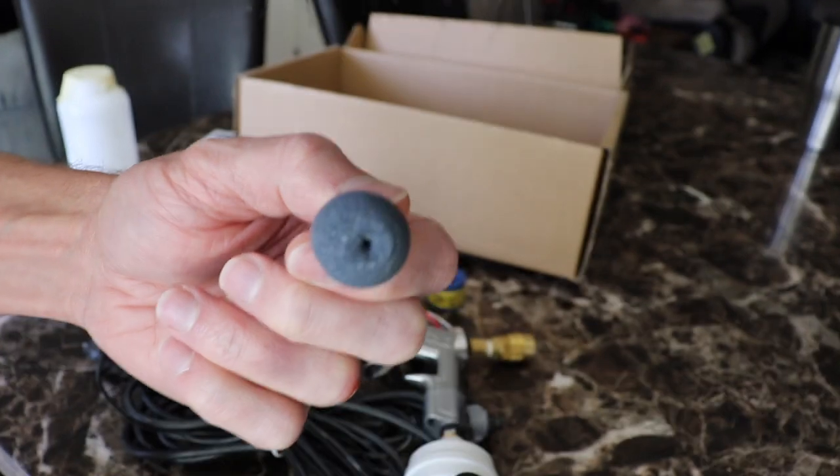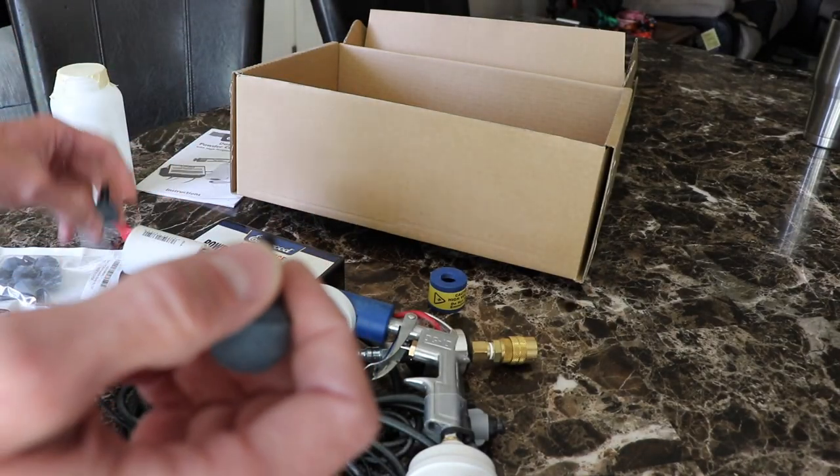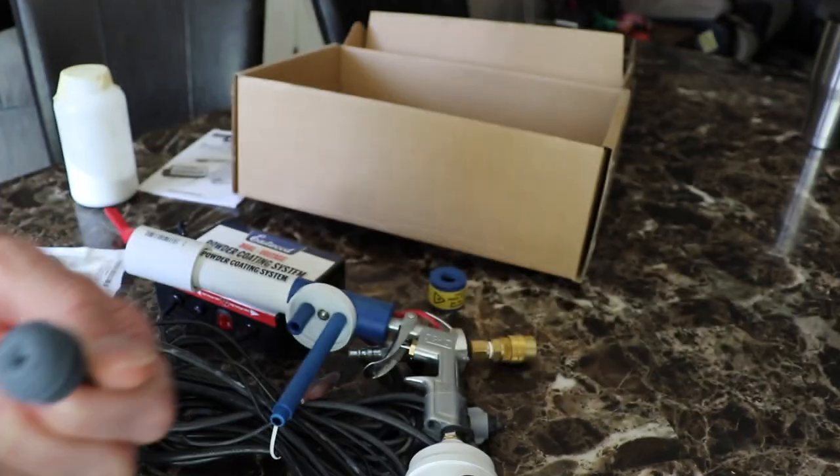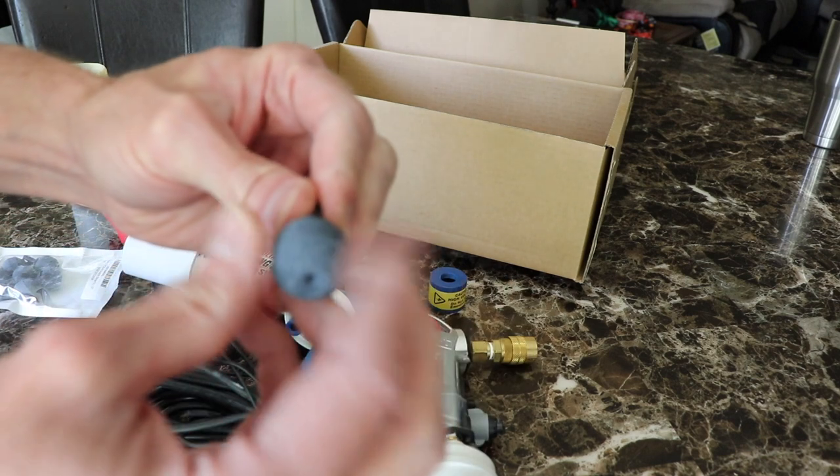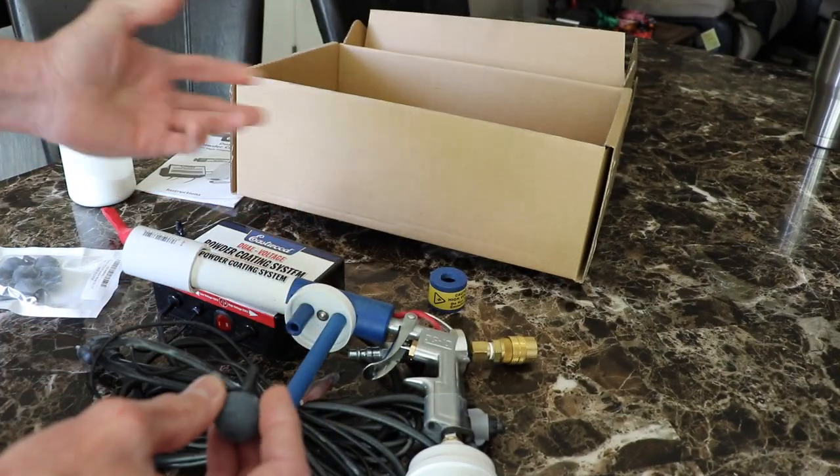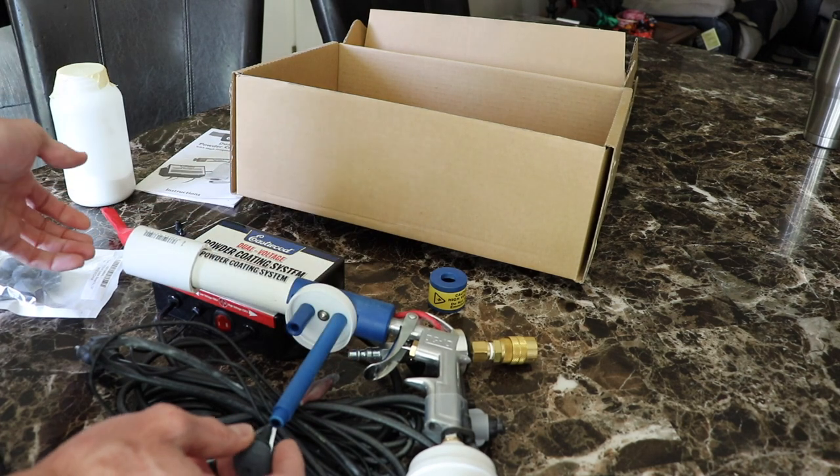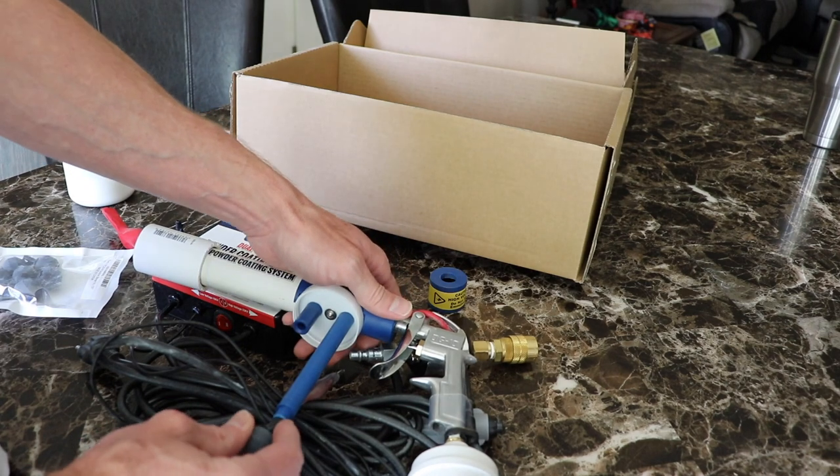But you will have to run a little bit higher pressures putting these air stones on. I usually run about 15 psi instead of 10. It doesn't increase my flow out of the gun because this is being restrictive. So it's not running 15 psi out of the tip of the gun. It's reduced down.